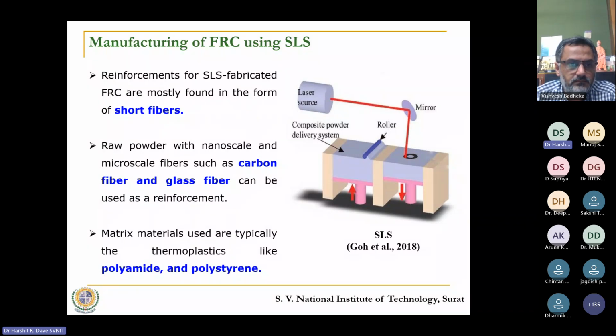Finally, we use a process called selective laser sintering for creating fiber reinforced composites. Here, short fibers are only preferred. They are created in the form of powders, and they are evenly mixed in a certain proportion with the polymer powder. And then this carbon fiber or glass fiber plus polymer is spread by the usual rollers along the surface, and its curing is done with the help of a laser. So just as the single polymer is fused with the help of a laser, in the same way this polymer plus fiber mixture is also fused together. Usually polyamides and polystyrene are the thermoplastics which are being investigated by people with SLS.